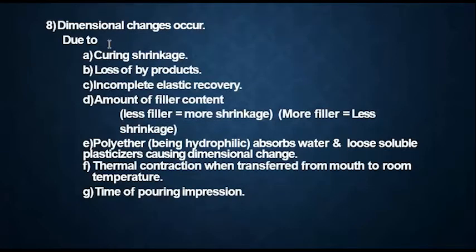Here, dimensional changes occur due to curing shrinkage, loss of the byproducts, incomplete elastic recovery, and the amount of filler content. Less filler, you have more shrinkage; more filler, you have less shrinkage. Polyether, being hydrophilic, absorbs water and loses soluble plasticizers, causing dimensional changes to occur. Thermal contraction, when transferred from the mouth to room temperature, also occurs, and it is influenced by the time of pouring the impression, whether you pour it immediately or after 1 day or 2 days.